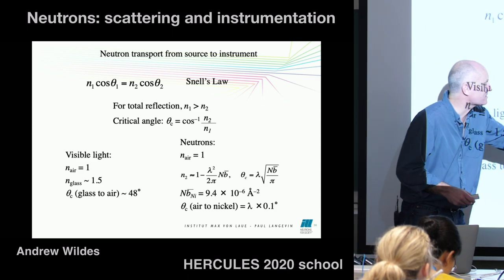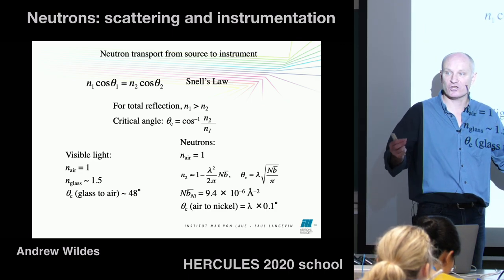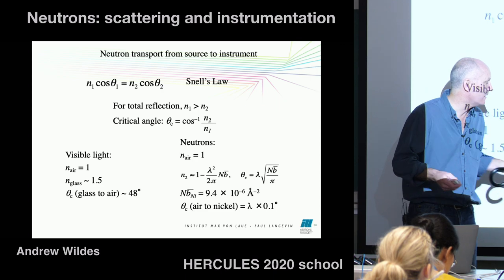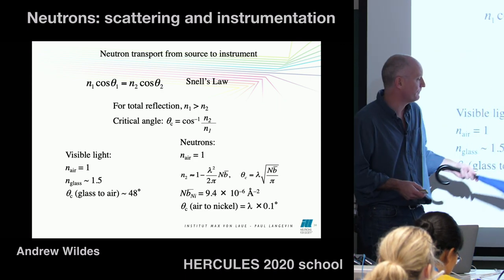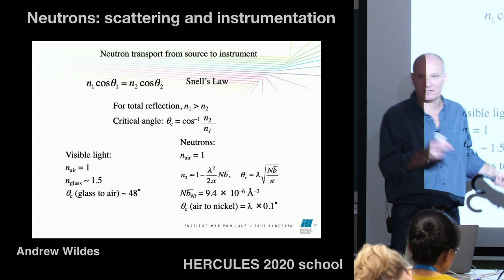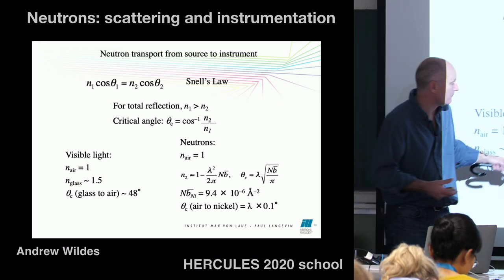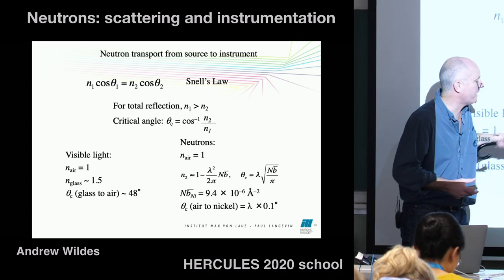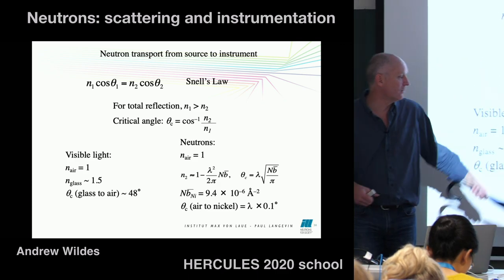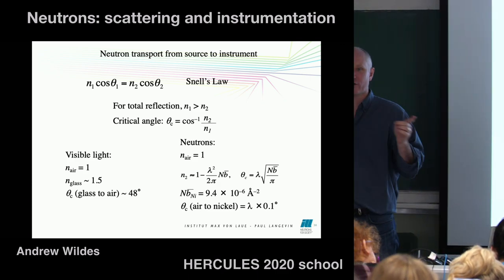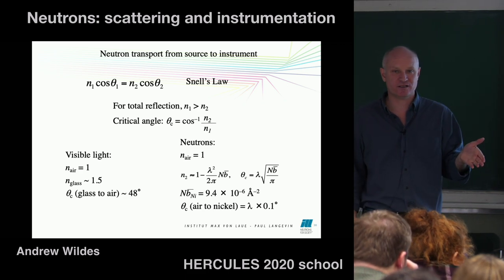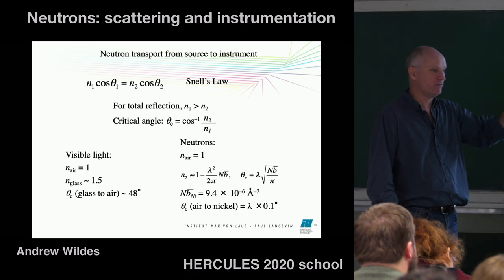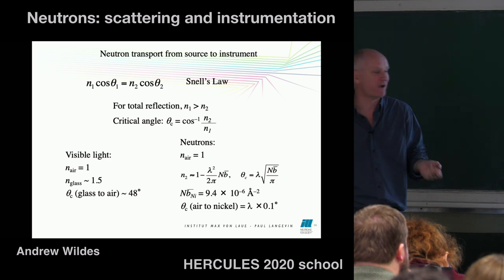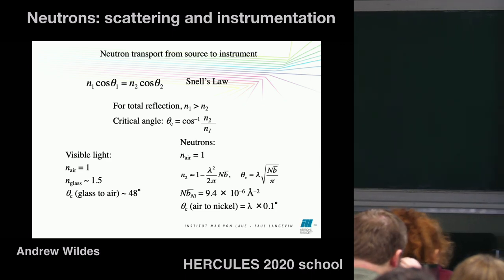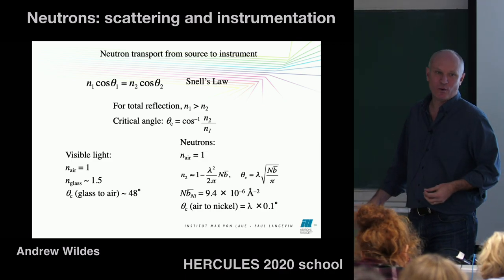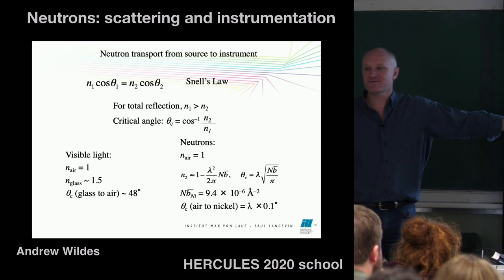So it's one minus this coherent scattering length, which, by the way, is the coherent scattering length I was telling you about yesterday. And that coherent scattering length is one of the biggest for nickel. It's about this quantity here. If you multiply these up, you realize that the critical angle is about 0.1 degree multiplied by the wavelength you're interested in. I showed you yesterday that thermal neutrons have a wavelength of about 1.5 angstroms. So that is very small. 1.5 angstroms is 0.15 degrees.